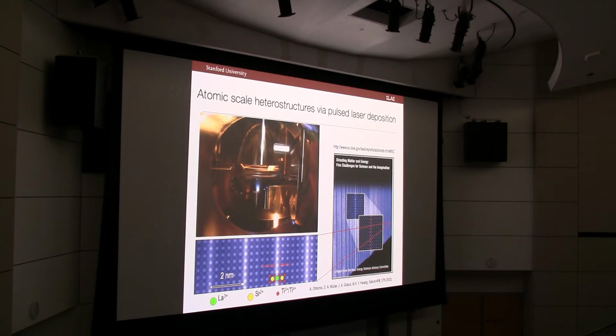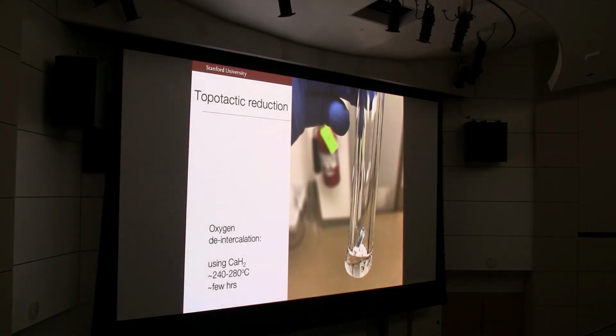So this is a rather, let's say, expensive and elaborate technique, and this is how we're growing thin films. This is actually another perovskite, so this is how it looks by electron microscopy. This is a 4 angstrom building block, and this is the way we grow our starting thin films. And then the key additional step looks very simple and primitive.